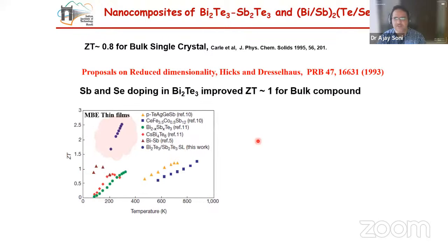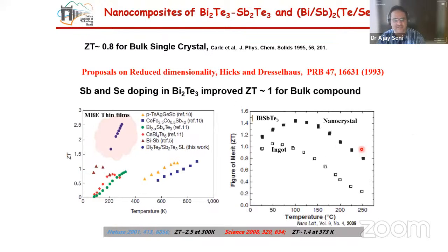And now, another aspect, so this is the final example for my talk. I'll talk about bismuth telluride, which is another champion material, and a lot of research has been going on in the last 10 years or so. From the 1950s to 2000 or so, the figure of merit for the bismuth telluride based materials was around 0.5, or it reached around 1 in almost 2008 or something, which was published in Science by one of the Boston and MIT groups. So you have a bulk material which has the efficiency like this one, and what you do is you break them, and then you make a composite out of it again, and you have the nanocrystals, so the efficiency increases. The figure of merit has gone up to 1.4 or 1.5. Now it has gone to 1.8 or 2 in these kinds of materials.